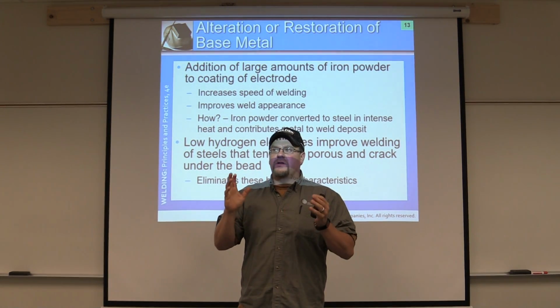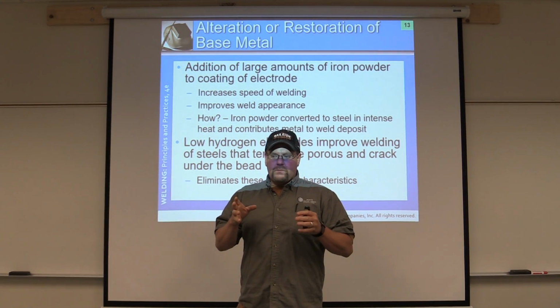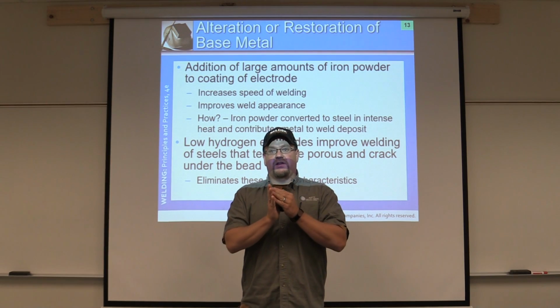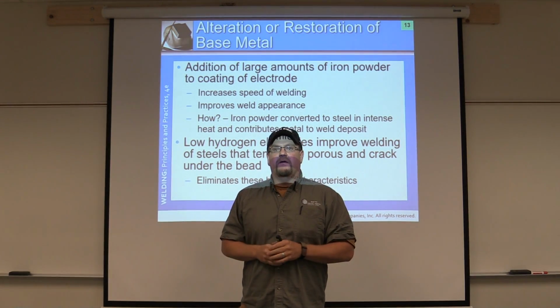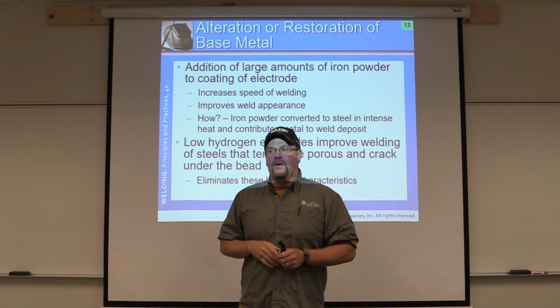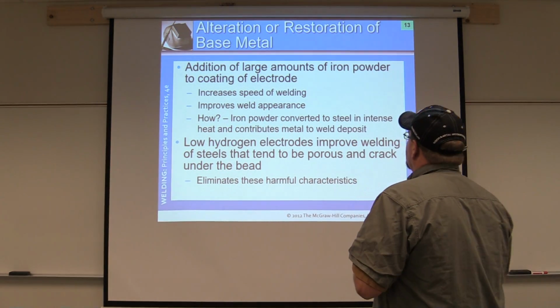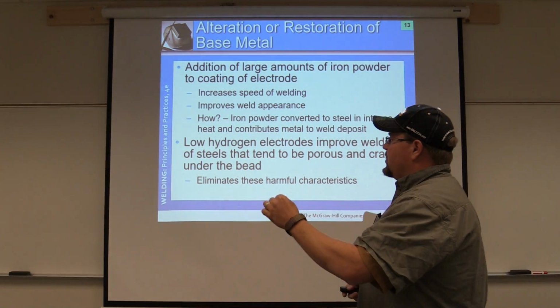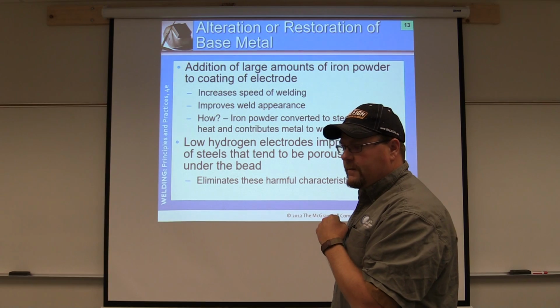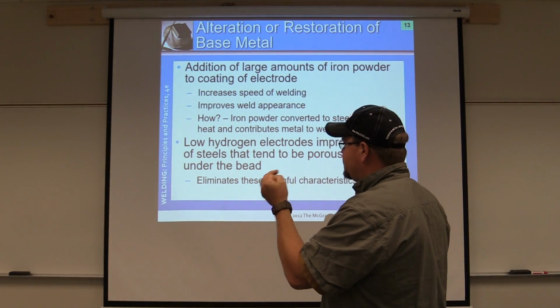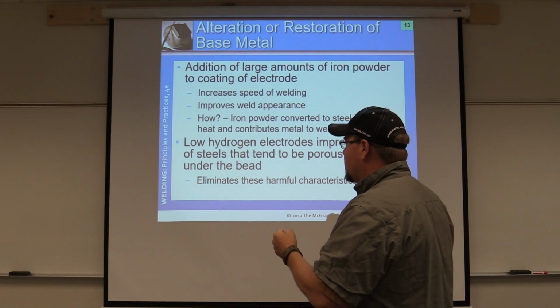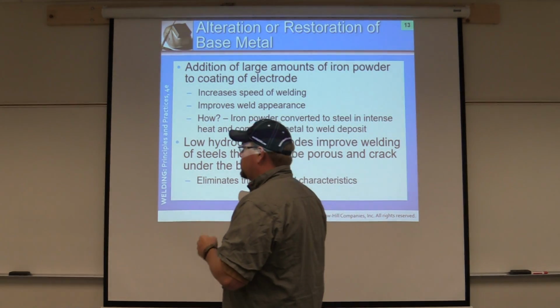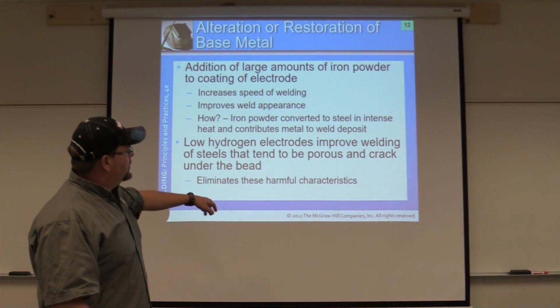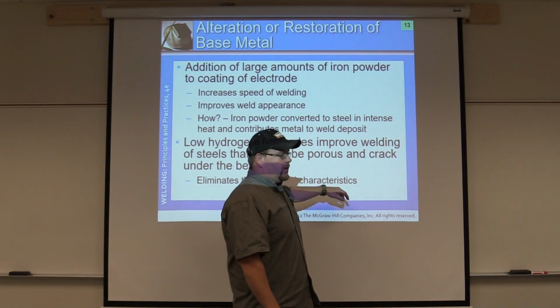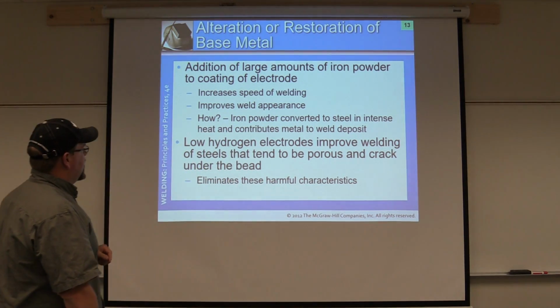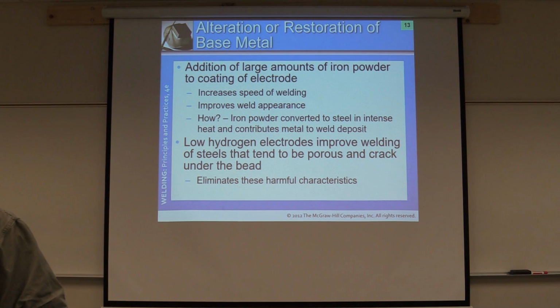It'll start cracking, and cracking is the number one failure in all welds, because there's literally no more metal fusion there, okay? They're two separate pieces at that point. And that's when we have catastrophic failures. So what we're going for there is the low hydrogen helps eliminate the process of hydrogen entrapment, porosity, and so forth. Again, it's still up to you to make sure that you perform the correct welding technique in order to aid and help in no porosity and hydrogen cracking. But the rod is designed to help improve.